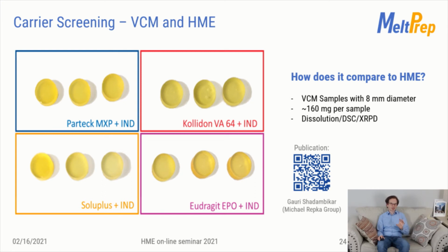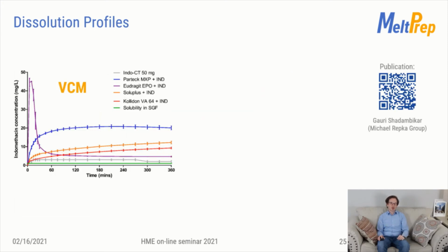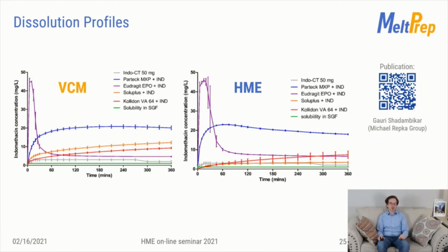I would like to highlight the dissolution data. The VCM samples were milled and then subjected to dissolution. One can see significant differences between the carriers. One unique feature that I would like to point out here is the performance of Parteck MXP, because you can see a very high supersaturation, which is obtained over a prolonged period of time without recrystallization of the drug. The same formulations were also processed via hot melt extrusion, milled and then subjected to dissolution.